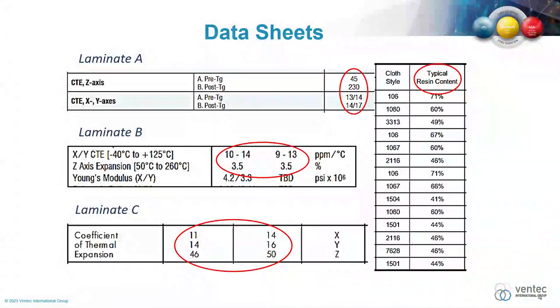The other thing a designer doesn't know would be the typical resin content from the fabricator. And that depends on the glass cloth style. I'm not going into how the material is actually manufactured, but a lot of different types of glass cloth will have much different resin contents. And even though some of these materials have a typical value, we can actually supply some of these materials at a lower and a much higher resin content when requested.